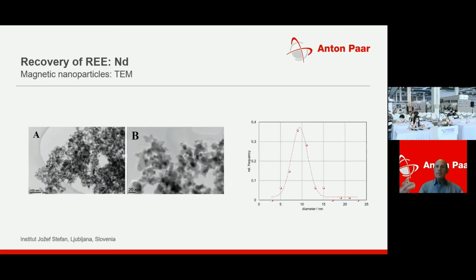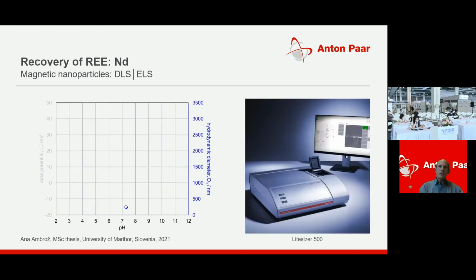To determine the size of the primary particles, we used transmission electron microscopy, which indicates an average diameter of 9 nanometers. But when we disperse the nanoparticles in an aqueous solution, a certain degree of aggregation takes place immediately, and the hydrodynamic diameter of these aggregates, determined by dynamic light scattering, is observed in the range of 250 nanometers.